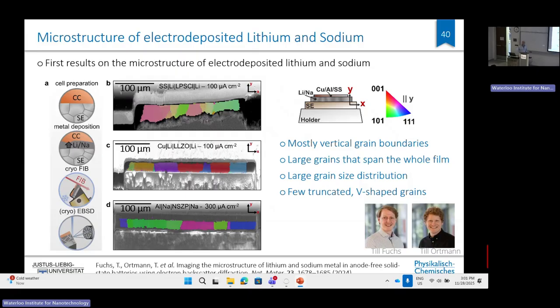So this is really electron backscatter diffraction, essentially electron crystallography, that only works if you have very clean, undamaged surfaces. Then you get the electron pattern, in principle the Kikuchi pattern. And the shocking result was that these grains are really huge. You see here 100 micron; in some cases they grew up to almost 100 micron grain size. So the idea to create small-grained lithium didn't work.